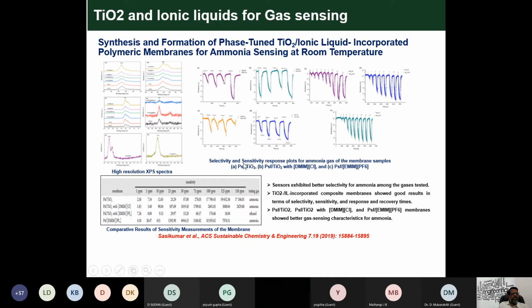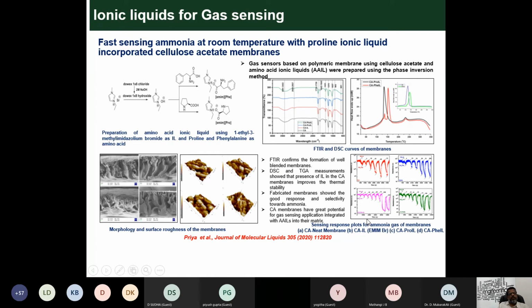See, in this work, the selectivity and sensitivity response plot of ammonia gas for the membrane samples. We collaborated with Shastra University and some other universities that are strong in membrane gas sensing. They were quite surprised that our material is very good for sensing, very fast, with a much higher response plot, and the selectivity is also very good compared to other materials. That encouraged us to keep working on membranes.